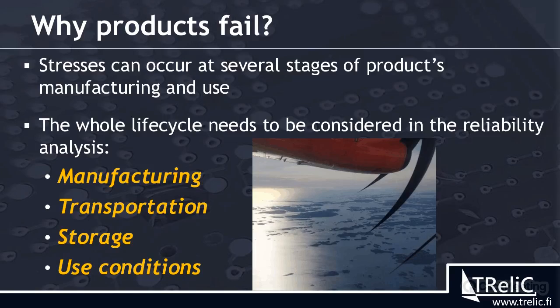So as I already mentioned, we can have failures due to manufacturing, due to different issues. So it's important when we consider failures to consider all the stages of the product's lifetime. So we have manufacturing, for example, in electronics where we work a lot, there are quite often high temperatures used in the manufacturing, and these can cause stresses to the structures, which later cause failures. And it is important to take these into account.